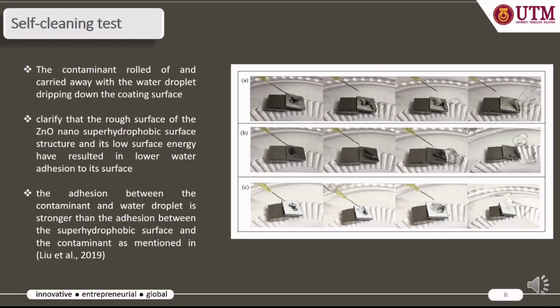The contaminant contained within the water remains on the surface of the EP resin, as shown in B, while a different tendency was observed on the zinc oxide nano superhydrophobic coating. The contaminant rolled off and was carried away with the water droplet dripping down the coating surface. This clarifies that the rough surface of the zinc oxide nano superhydrophobic structure and its low surface energy have resulted in lower water adhesion to its surface. Hence, the adhesion between the contaminant and water droplet is stronger than the adhesion between the superhydrophobic surface and the contaminant, as mentioned in Liu et al. 2019. The experiment validates that the fabricated coating has self-cleaning property and water repellency.